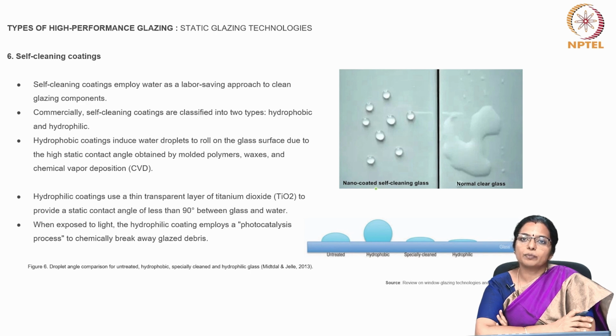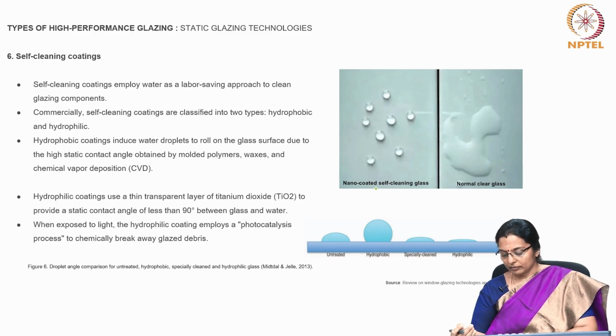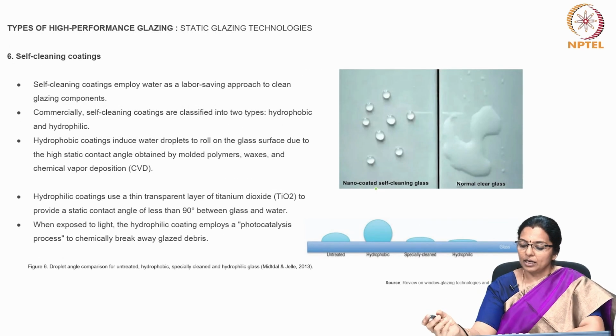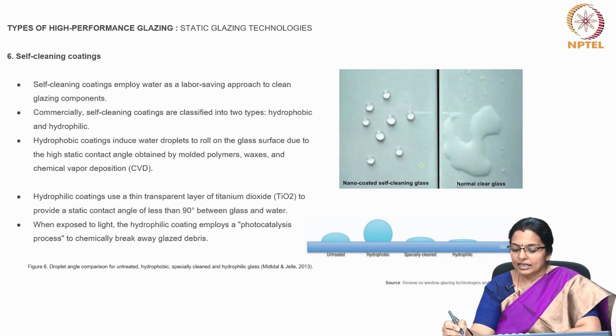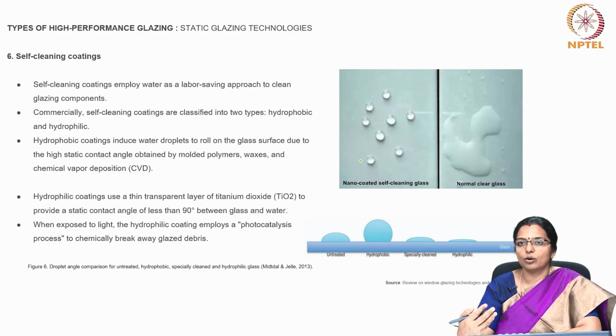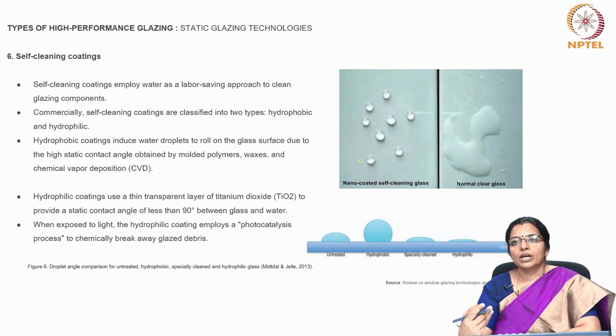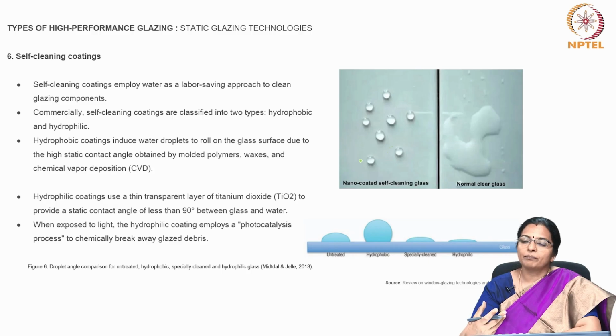Hydrophilic coatings use a thin transparent layer of titanium dioxide to provide a static contact angle of less than 90 degrees between glass and water. When exposed to light, the hydrophilic coating employs a photocatalysis process to chemically break away glazed debris. Normally, for nano-coated self-cleaning glass, titanium dioxide is used, and in the presence of dust, it combines the dust particles along with the water and slides down. Because of the use of this glass, a lot of economic savings is made, especially for glasses of high-rise skyscrapers, where otherwise humans have to be employed to clean the glass from outside.